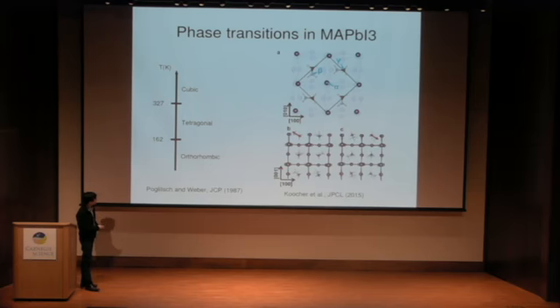I'll just briefly go through the phases again. As we know, the low temperature phase is orthorhombic, same as in the bromide structure, and then it becomes tetragonal, and finally the high temperature phase is cubic. It is a perovskite structure, the inorganic part is perovskite, and the organic part, in this case CH3NH3 molecules, is arranged at the A site.